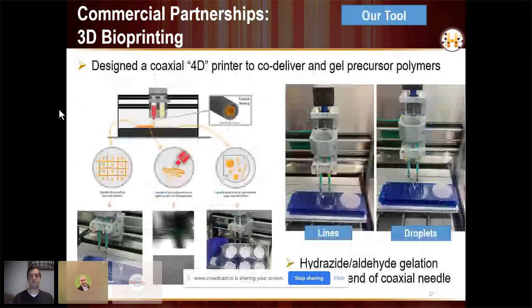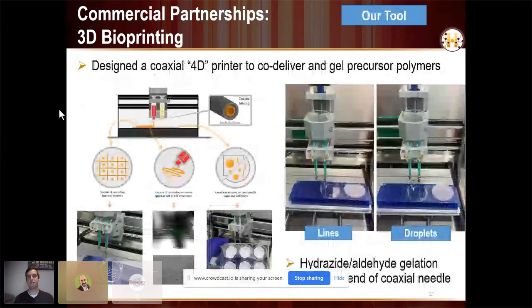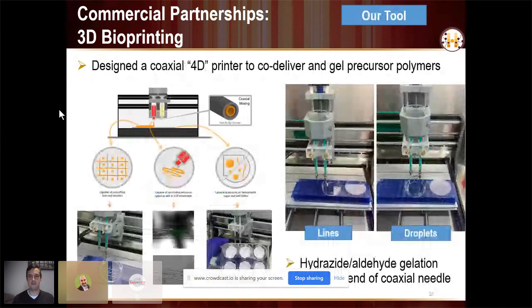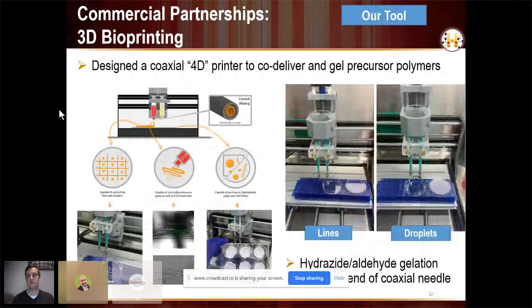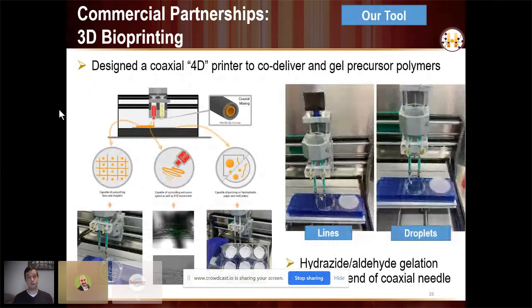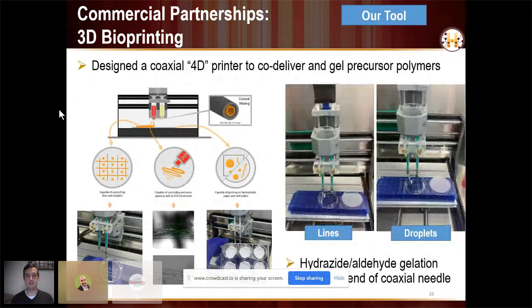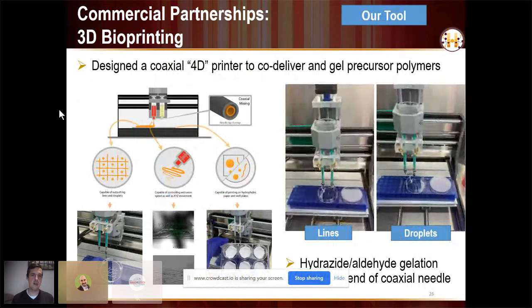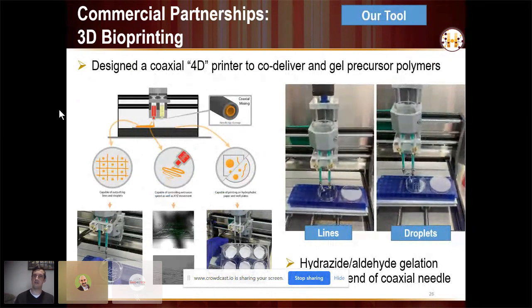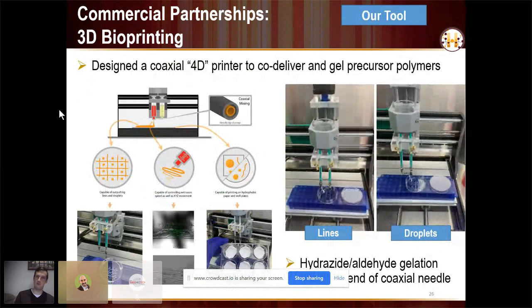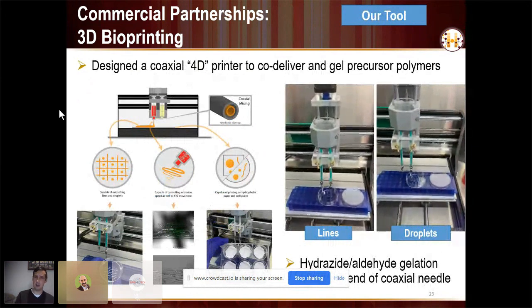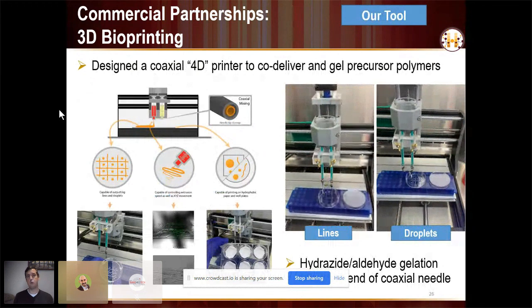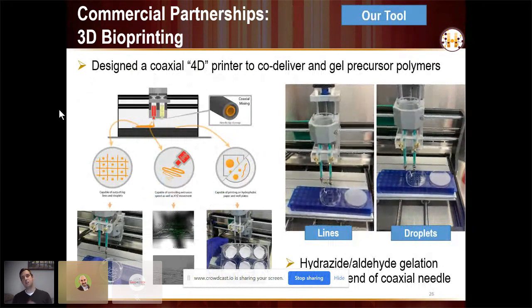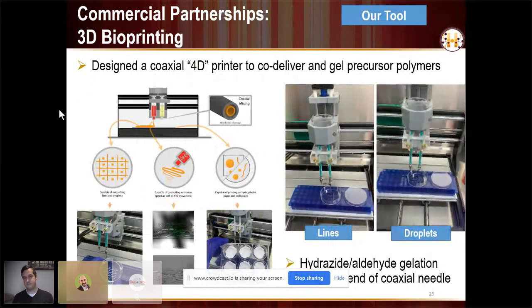So what we've done is a couple of strategies. The first is we designed a coaxial 4D printer, and this is a custom-built thing with components off the shelf, which we could use to co-deliver these reactive functional precursor polymers and create printable hydrogels. So what the tip looks like is basically a smaller needle in which we print the hydrazide component typically, and cells if we want to print cells, then an outer needle where we deliver the aldehyde component.